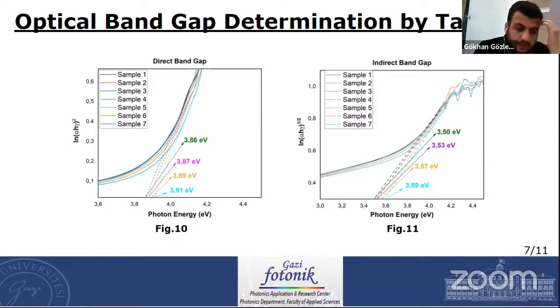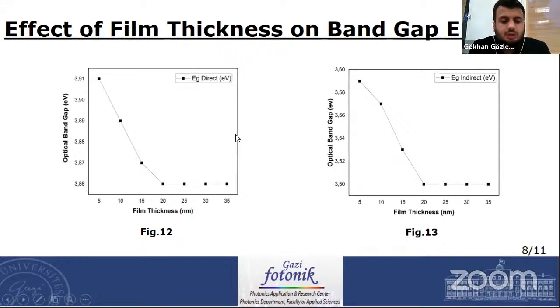It's known that band gap determination by Tauc plot isn't precise, but I want to highlight that in the figures, the straight portions of sample 7, sample 6, and sample 5, which have thicknesses of 5, 10, and 15 nanometers respectively, do not overlay each other. There is a difference between them, but from sample 1 to sample 4, the straight portions of the curves overlay. These results show there is no change in band gaps for films thicker than 15 nanometers. It means the quantum confinement effect is observed just in films thinner than 15 nanometers. Beyond this thickness, films behave like a bulk material.